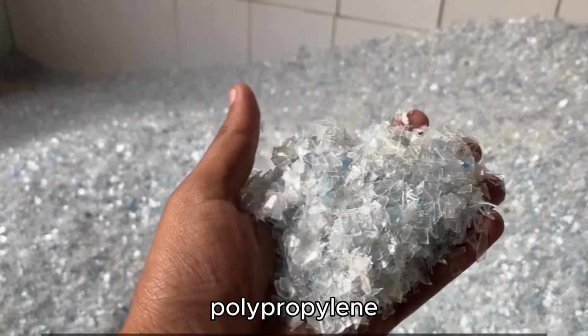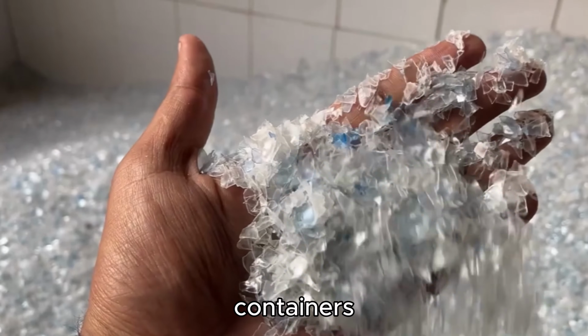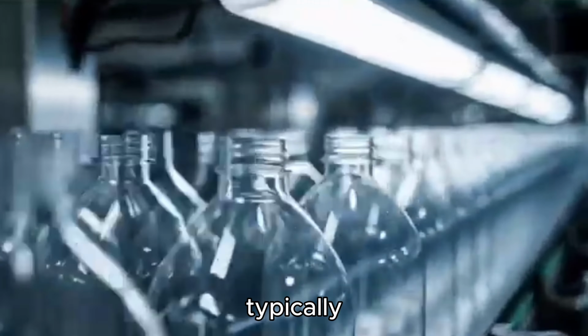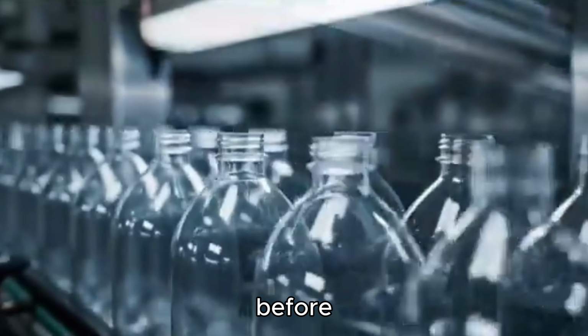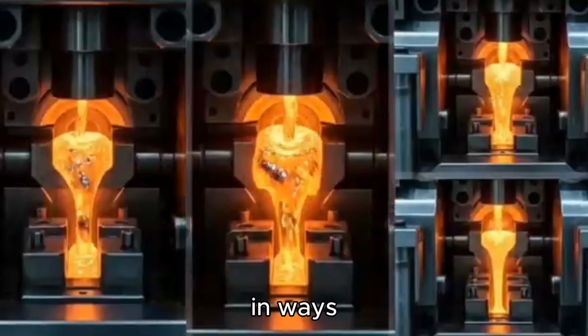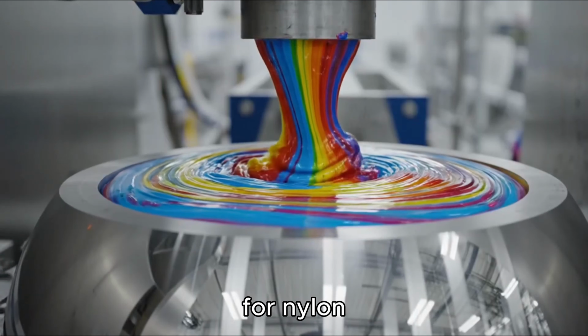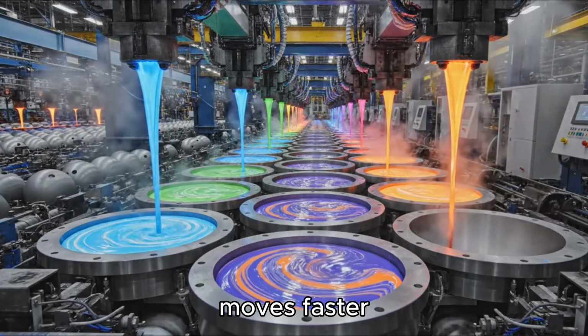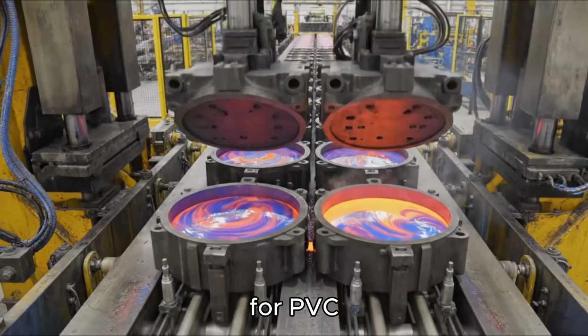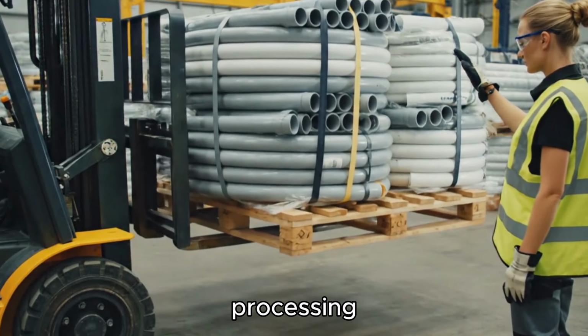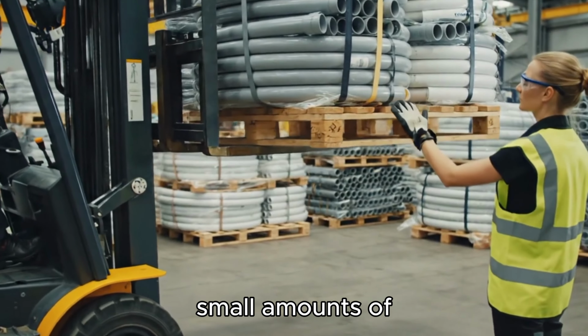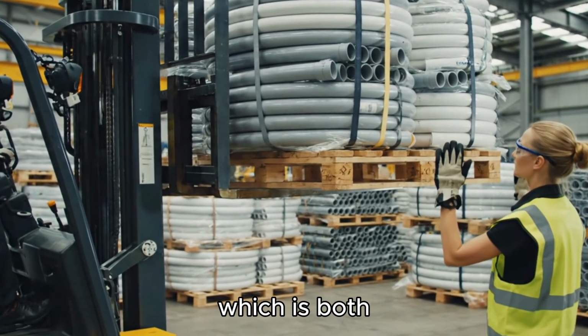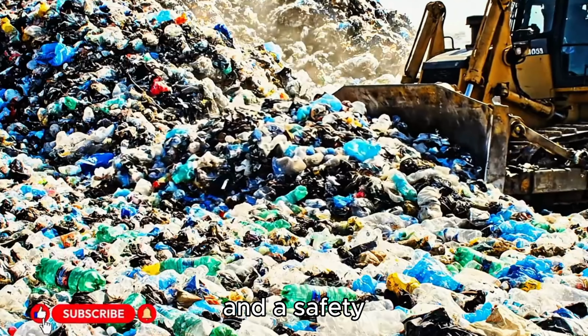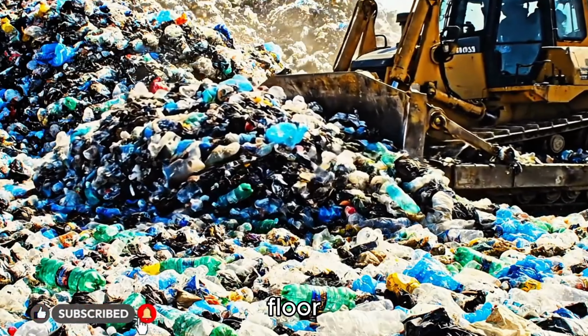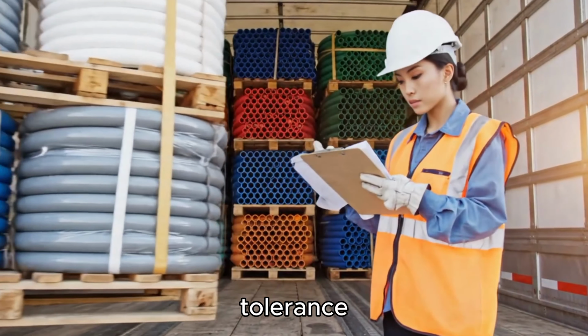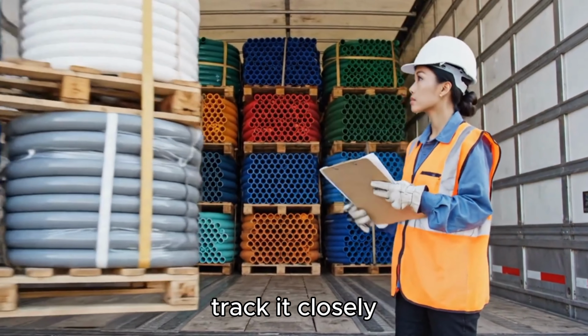For polypropylene, which shows up in everything from food containers to automotive trim, you can typically run 1 or 2 regrind cycles before mechanical properties start drifting in ways that matter. For nylon, thermal degradation moves faster and hits harder. For PVC, repeated heating is a real processing headache. It can start releasing small amounts of hydrogen chloride, which is both a contamination concern and a safety issue on the production floor. Every material has its own tolerance, and experienced process engineers track it closely.